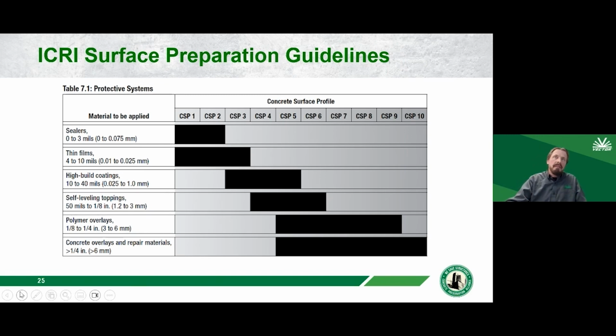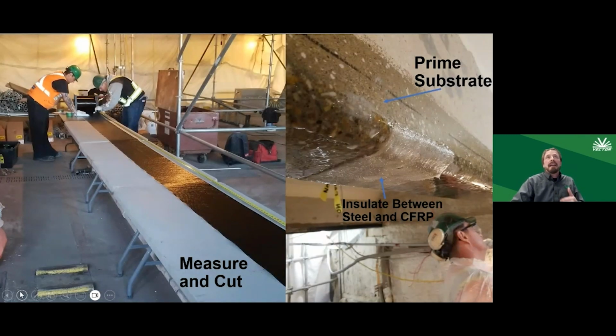Typically, that's achieved by, like I said, a very aggressive disc on a grinder or sandblasting. This holds true with all coatings that go on concrete. Typically, you're going to see a concrete surface profile identified by the manufacturer, and we want to make sure that we achieve that concrete surface profile prior to the installation of either the FRP or a coating. Once we've done the surface prep and it's to the correct profile, we're going to get into the business of installing the FRP itself.